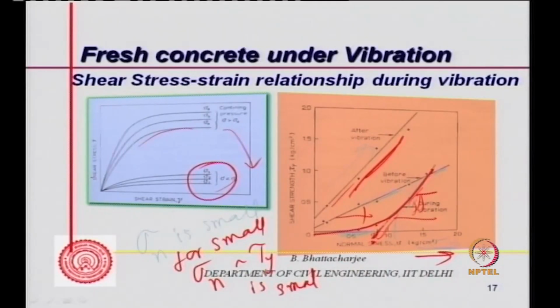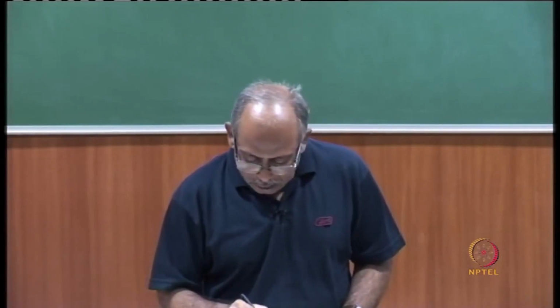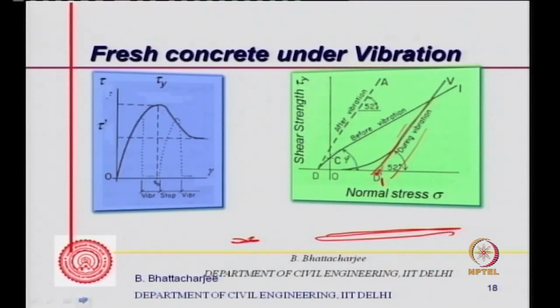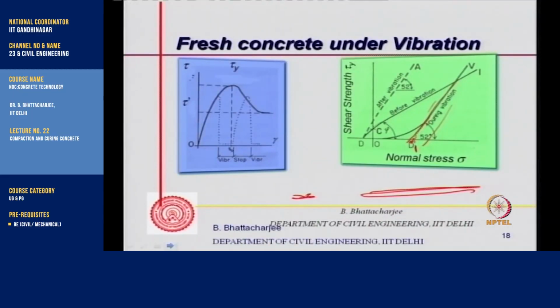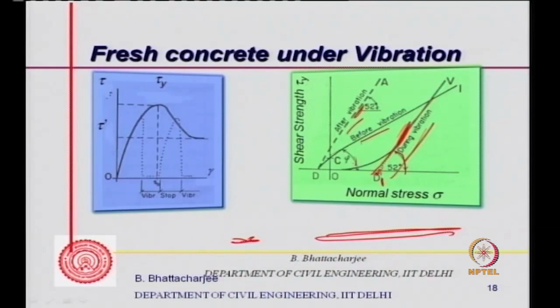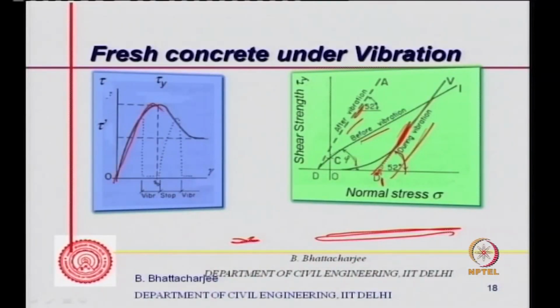And after vibration, it stiffens; the yield shear stress has gone back to some higher value. Once you stop the vibration, the cohesiveness is re-established, and that's how the behavior is. So it would again show up the strength part of it. The same thing is shown here: during vibration, before vibration, and after vibration. So this angle also increases. This angle is more or less similar, while this angle is less. So actually your tan phi, mu sigma, the tan phi has increased, the angle of repose has increased. That means it can stand on its own, stiffer, at a steeper angle. And this diagram also shows you something like this. This is before vibration.